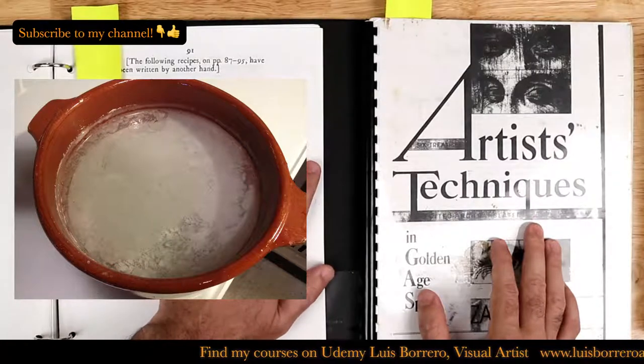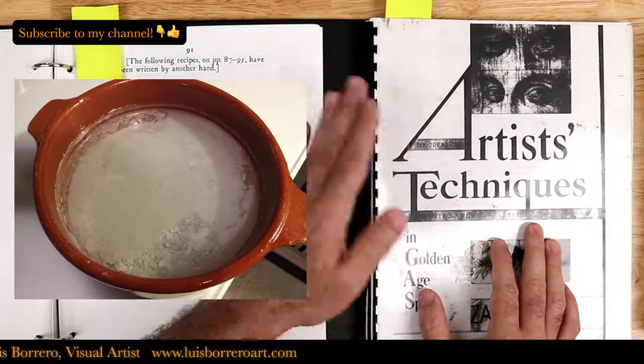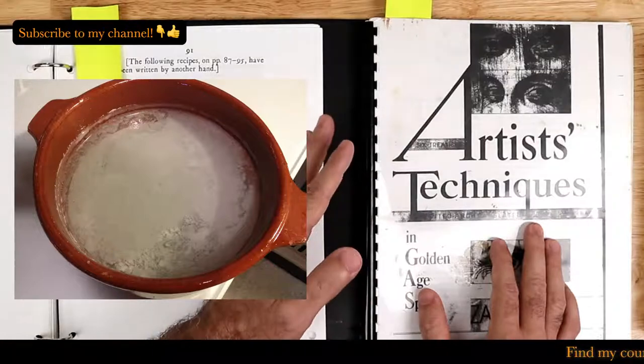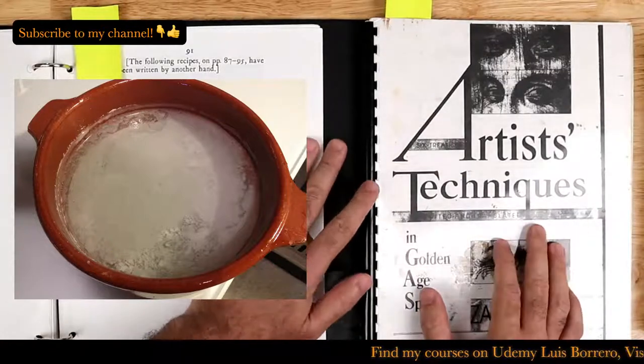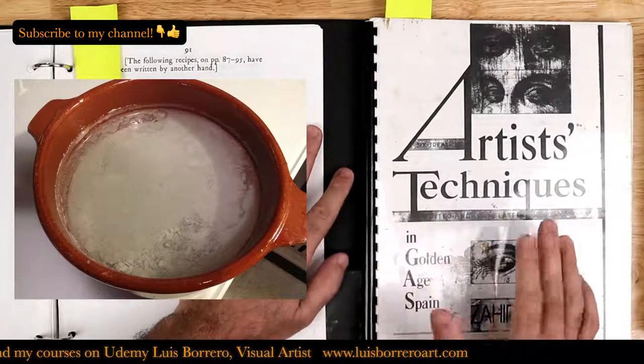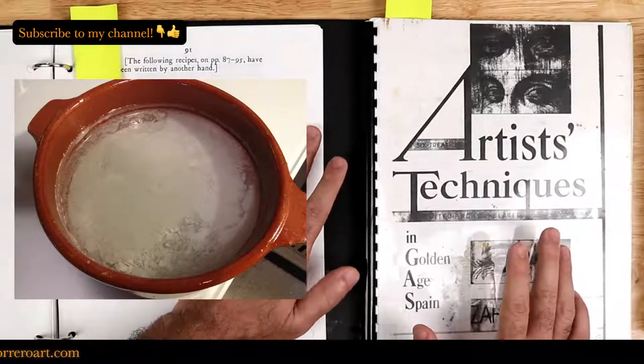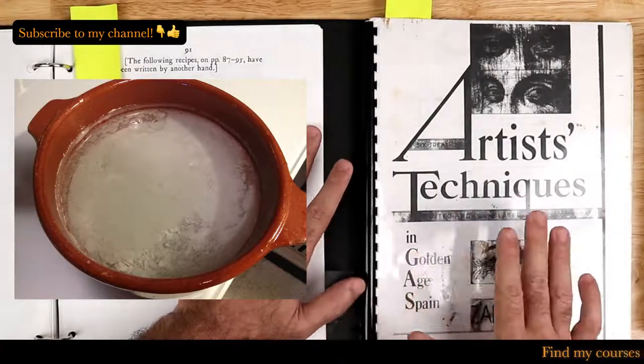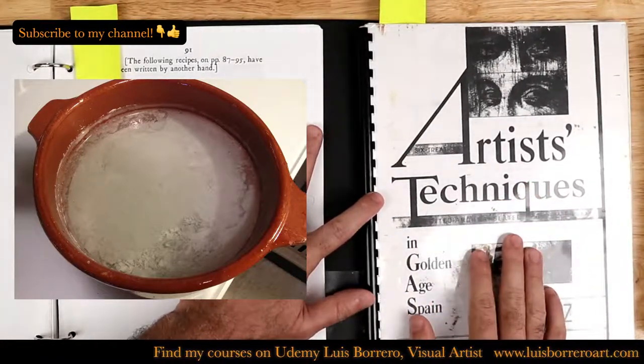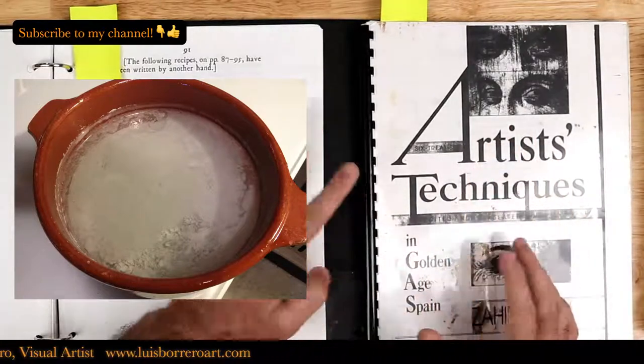But Norgate gives a clue to change the water at least 12 to 13 times, and I found that's about the right amount of times to change the water until the pigment is fully clean. In this picture, you see the lead acetate floating on top of the water, and the non-soluble basic lead carbonate sinks to the bottom. And that's how you separate both.